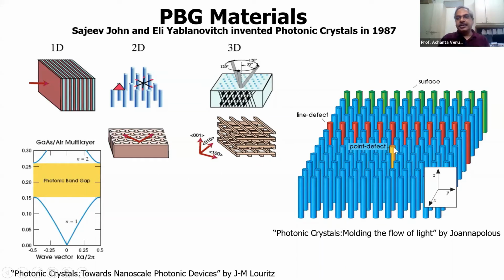So what happens if you put a quantum dot at the position of this defect? Light is emitted at the defect mode wavelength or frequency. That frequency is within the band gap region for this periodic structure. So all the surrounding rods, the periodic structure, are going to reflect and scatter the light back into the defect position. So it acts like a microcavity.